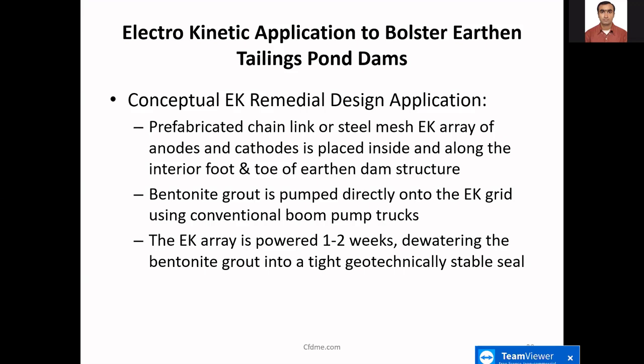Another thought that came up too was to take a network of electrodes, and if it's exposed to the surface, you're going to see some fracturing in the top of the clay. One of the areas that we looked at, as these fractures develop, was to fill those with bentonite and apply the electrokinetic force to seal these things up in a much better, more consistent manner.